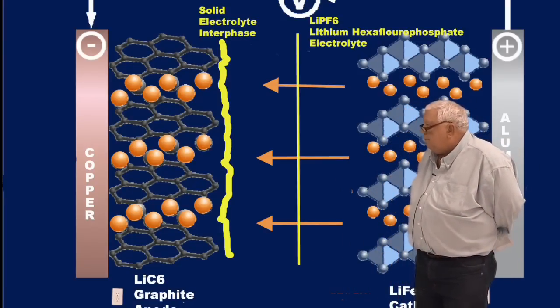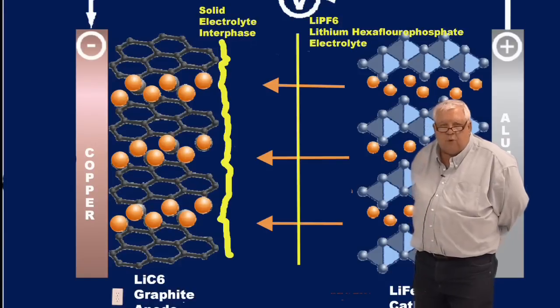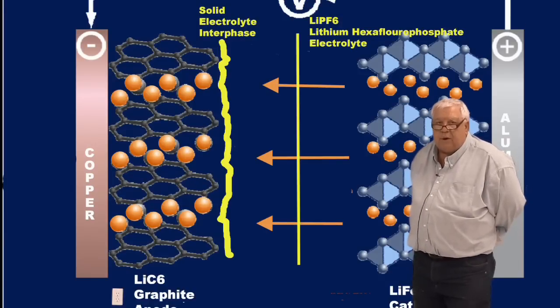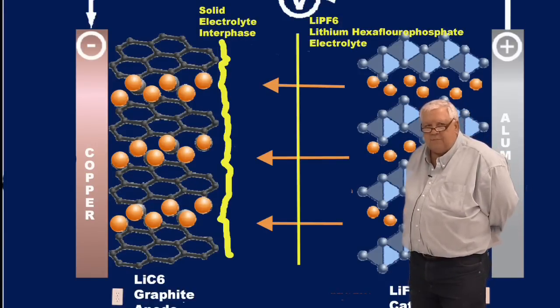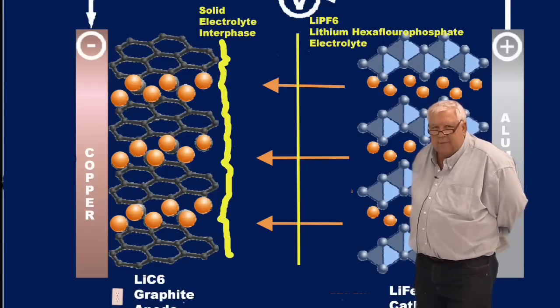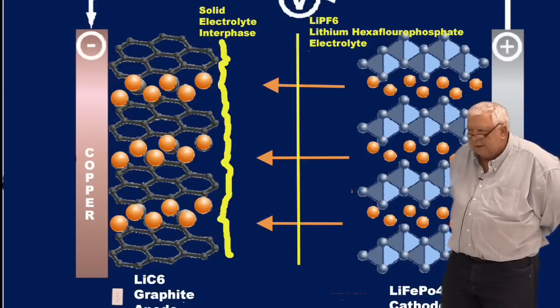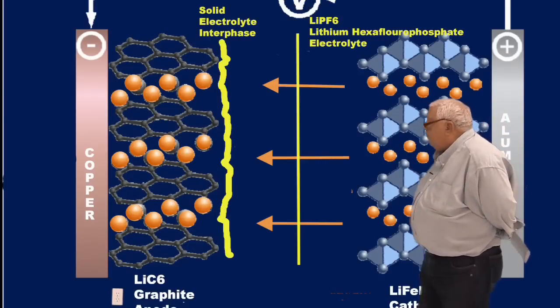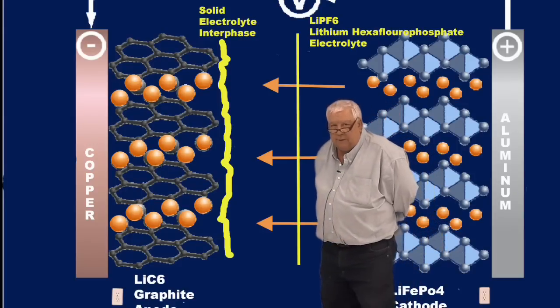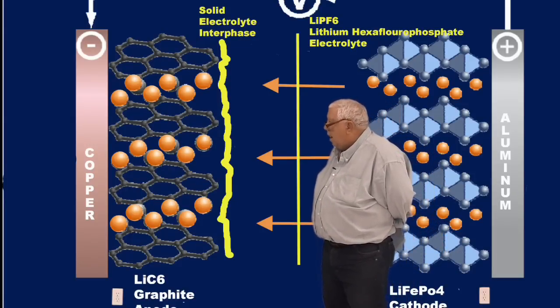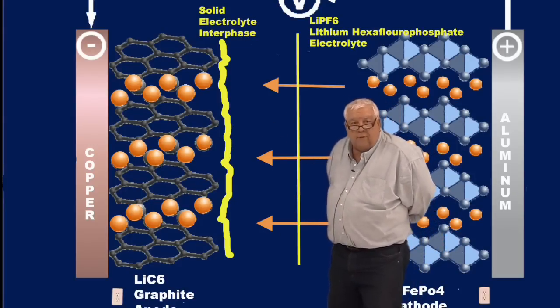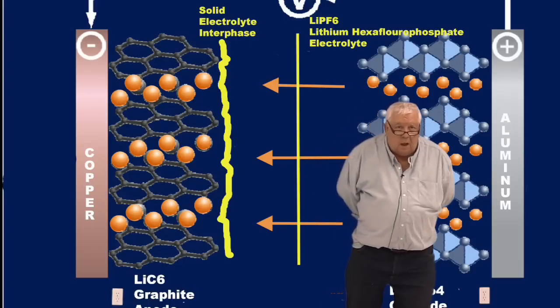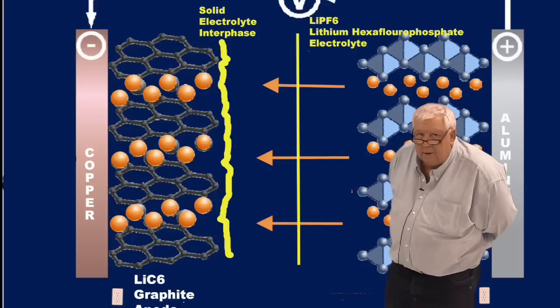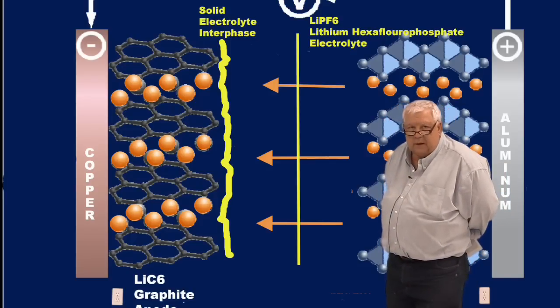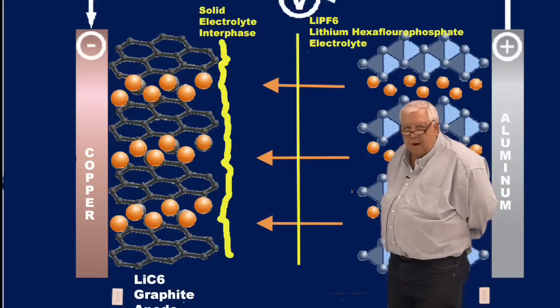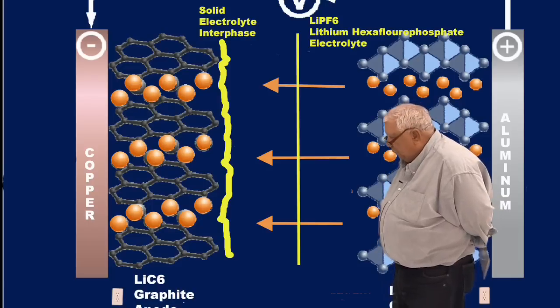between getting the lithium ions through the SEI layer, which they can penetrate. Lithium ions are very small, much smaller than any of the atoms and molecules in the electrolyte. And so they can diffuse through it, but it delays it, and it actually causes a little bit of a voltage drop. That voltage drop, as we increase our current, for example, in fast charging, if it reaches a certain point, it will cause a rupture of that SEI layer and a fairly catastrophic runaway situation then.